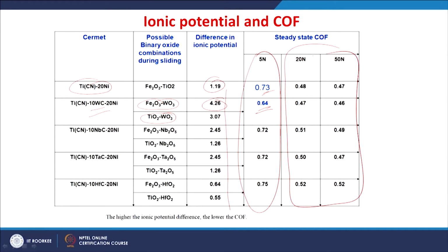That indicates that whenever the wear is dominated by the mechanical aspects, the abrasion, pull out and fracture, then you have the effect of these oxides and the respective difference in the ionic potentials on the friction behavior. Whereas at higher load, we have seen the surface is completely covered with a tribo layer rich in oxides, particularly the iron titanium oxide. So, it is actually happening like this: the surface is filled with the oxide.